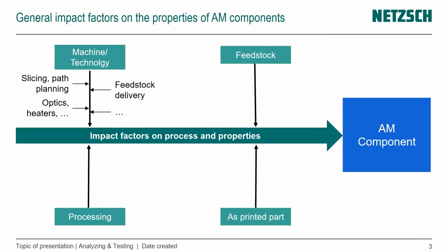Next we have feedstock, which we've already talked about the most. There we can first look at the production of the feedstock. For example, if the powder is polyamide 12, it's very likely produced with precipitation, so it's a mostly spherical particle. But if it's another material like polypropylene, it's probably done by cryogenic grinding — so we'll have a very different surface, and that has an effect on the coating and the feedstock in general.